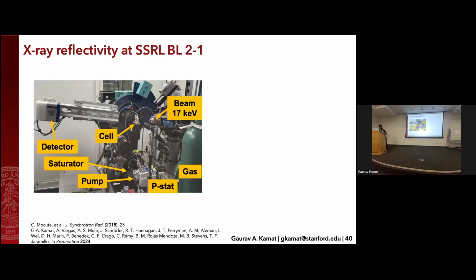Moving on to the other thing I mentioned, which was the anion distributions. So we use X-ray reflectivity, again, at the Stanford Synchrotron Radiation Lightsource. And this is a very familiar setup because you actually use the same exact cell. You just perform a slightly different alignment. And now your detector, instead of being a two-dimensional detector, is on this long arm that's much further out so that you can measure very slight changes to your signal.